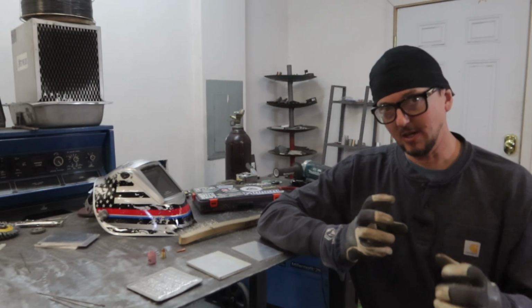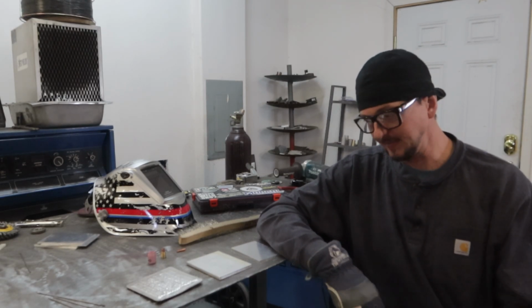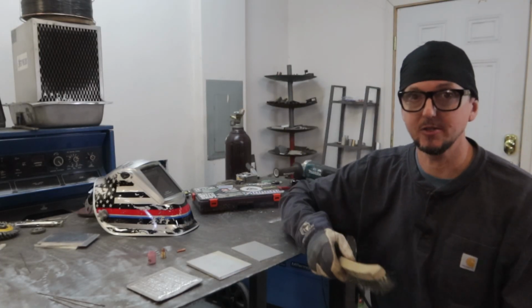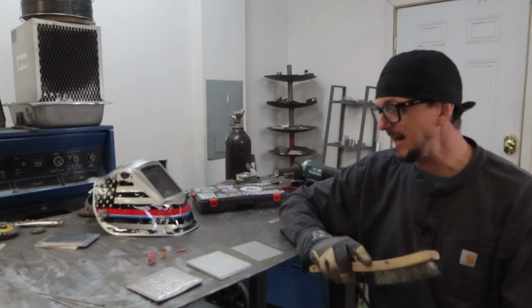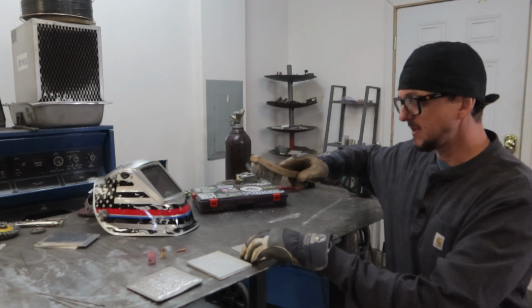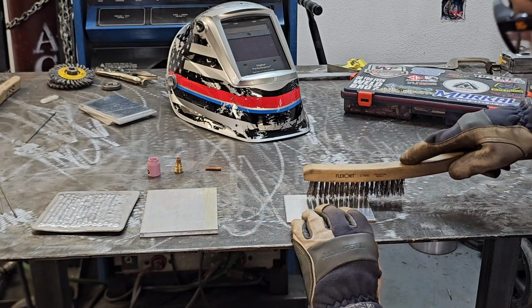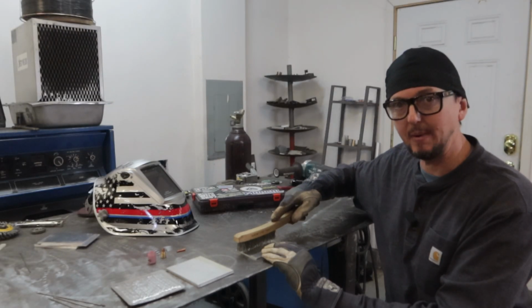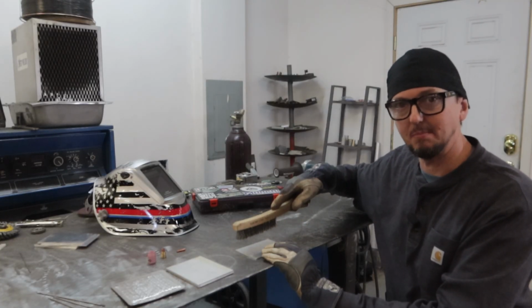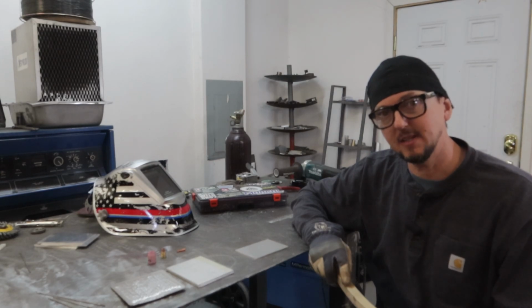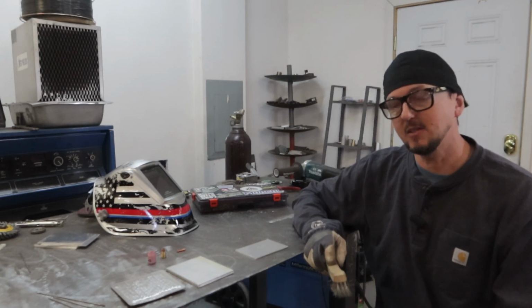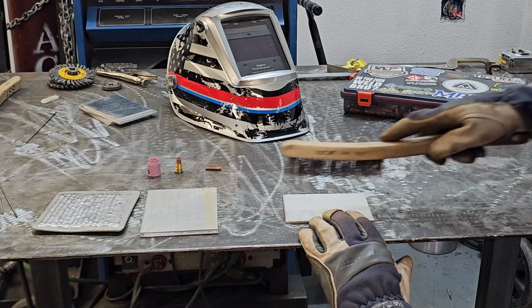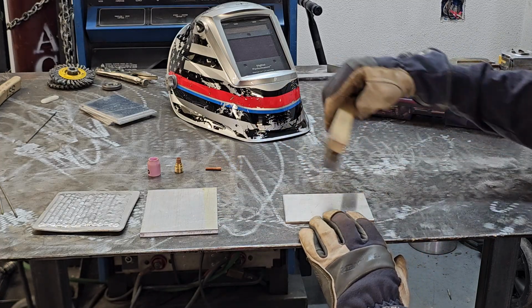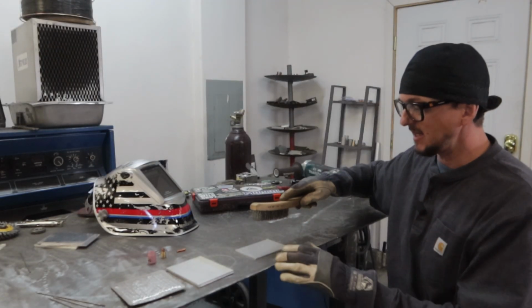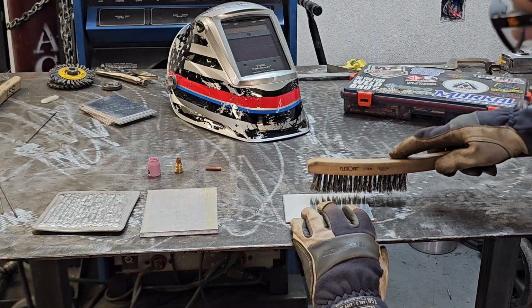And then you'll also see it'll start to contaminate that weld pool as it starts to break up. So we need to clean that up first using a wire brush. The important thing is that we lightly use a nice even pressure on the material as we go back and forth, not pressing too hard because that can embed the oxide layer into the surface of that soft aluminum material. We also want to only use one direction. Don't change directions because that can also embed it in there. Just a nice even pressure. So I'll show you how we do that now. I'm just going to pick one direction.